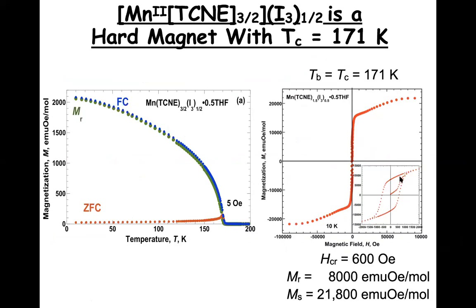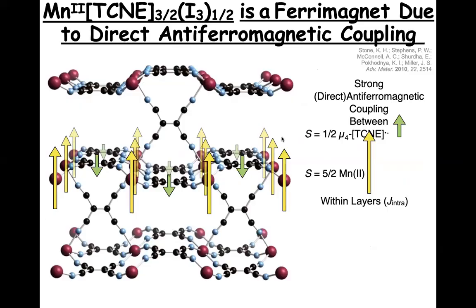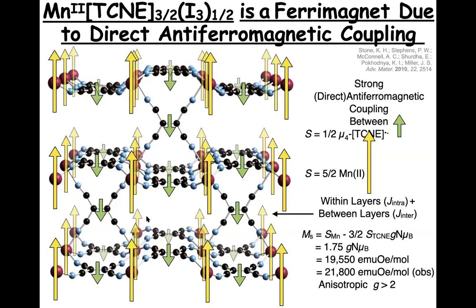So just changing the solvent leads us to a material that's a bulk ferrimagnet, and the coupling you can recognize is going to be the same in the layer, but now the TCNE radical anion above and below also have a spin on it besides the 4 in the plane. And the one above and below couple antiferromagnetically with the manganese they're bonded to in the layers above and below with it. So all the spins throughout the solid are in the same direction. And so it's a net spin 5 halves, manganese up, spin 1/2 TCNE radical anion down, bulk 3-dimensional ferrimagnet.